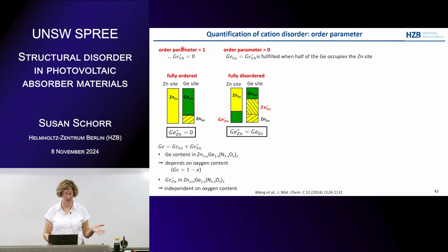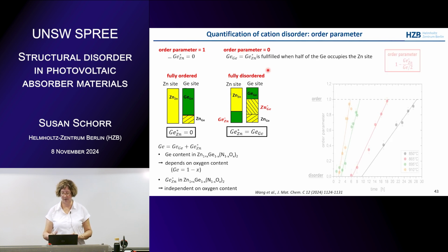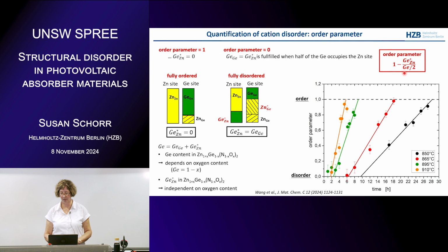We want fully ordered to be 1 and fully disordered to be 0. So we defined it like that. This is the order parameter we defined. It's the germanium on zinc star antisite intrinsic defect, and we have to divide by half of the germanium content. And then we got this figure.